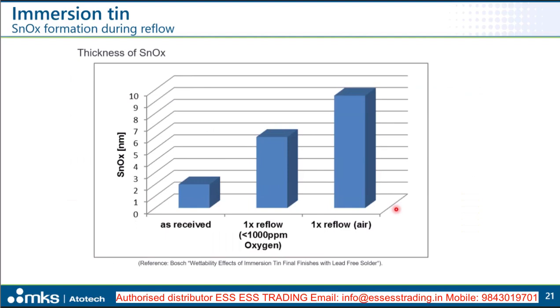So this needs to be kept in mind when talking about immersion tin layers aging during the assembly process. As mentioned, the tin oxide layer also grows during the assembly process. These are values which were published in a PhD thesis from Bosch a couple of years ago, where tin oxide was measured as received, and then after reflow aging, comparing reflow aging under nitrogen and under air. And what you can also see is that when you have the reflow process under air, a stronger oxide layer is formed on top of the layer.